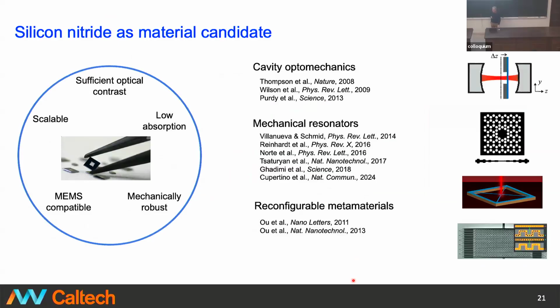So I guess our self-imposed mandate was, like the British monarchy, to present an heir and a spare. We wanted to have one good material candidate and then a second backup in case it didn't work very well. So our second backup was working with 2D materials like molybdenum disulfide, which has the material characteristics, but it looks like it's going to be, at least now, probably hard to scale in the same way as with silicon nitride.